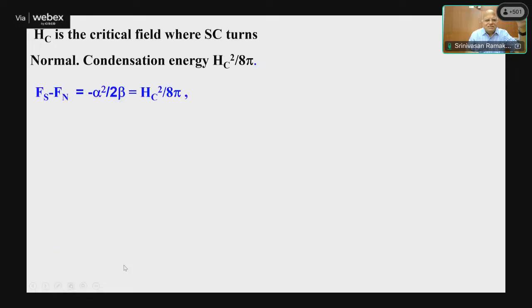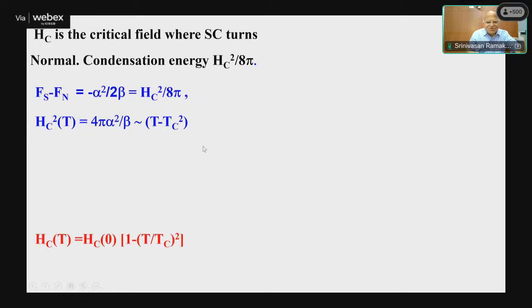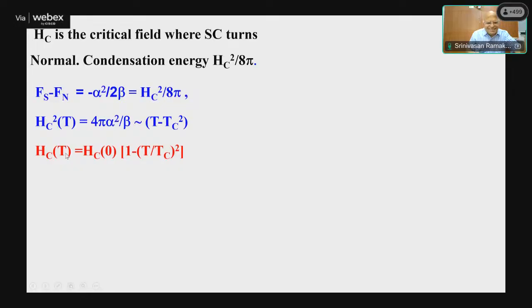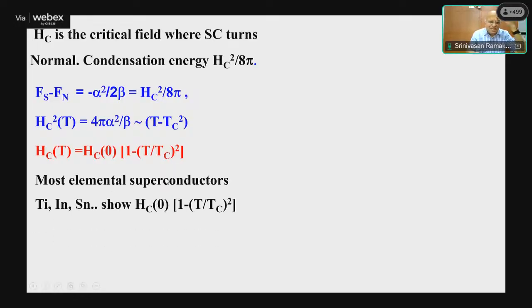And so one can also estimate the critical field by the free energy of the superconductor minus the free energy of the normal state, which is minus alpha squared by 2 beta. That's what we saw in the earlier expression, which is nothing but Hc squared by 8 pi. So this will give you an expression for Hc(T), the critical field, which is Hc naught times (1 minus t squared). This is what we saw earlier.